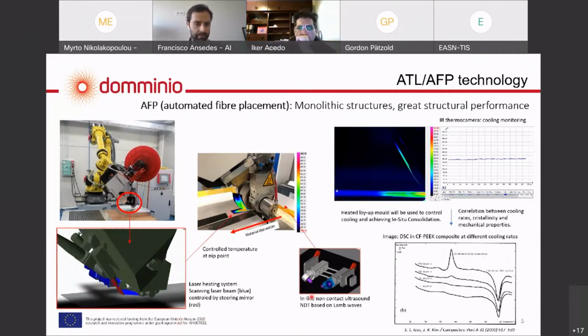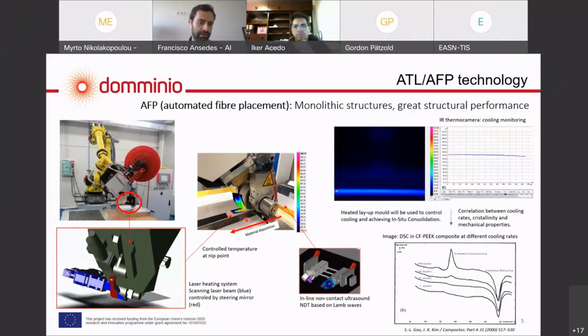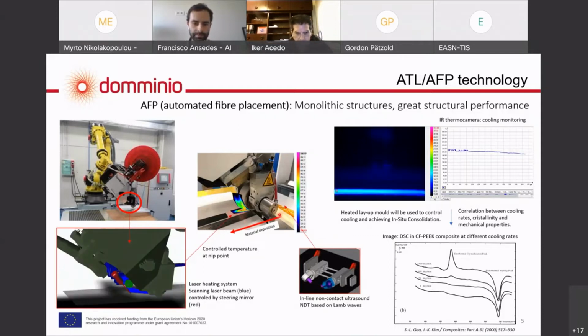Here you can see a picture of thermal imaging of the temperature that we take at the nip point. It is the point where we are pointing the laser, where the incoming tape that comes out of the machine and the substrate meet. We hit this point with the compaction roller, we apply pressure and we move the head. So we have a deposited and consolidated tape on top of the laminate.